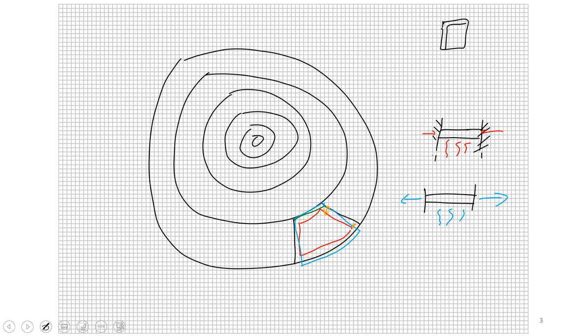So the red line is where all of the wood would like to be, and the blue line is where it actually is. Again, the black line is where it started out, the red line is where that entire section of tree would like to shrink down to, and the blue line is where it ends up shrinking under a partial shrinkage condition. So again, on the inner ring, it doesn't shrink much because that inner ring there hasn't actually lost much moisture. So out here on the outer surface, you end up with the wood having the shrinkage level that it wants. And then on the inside, there is very little shrinkage.